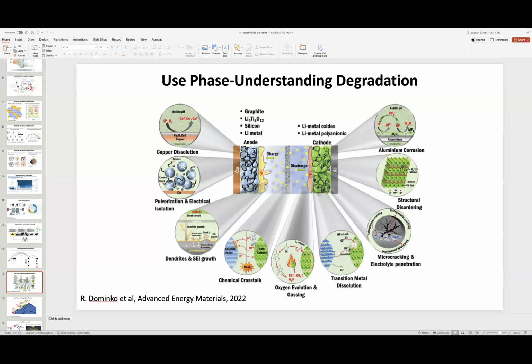Dissolution of the active materials themselves, forming HF. From the gas evolved, from the electrolyte decomposition, in particular when we use fluorinated electrolytes, but also this HF, we found out can come from the PVDF binder as well. Cracks of the electrode, mechanical degrading, filling these cracks with electrolyte, creating shortcuts, changing the structure of the cathode, and so on. So this is a very complex mechanism.